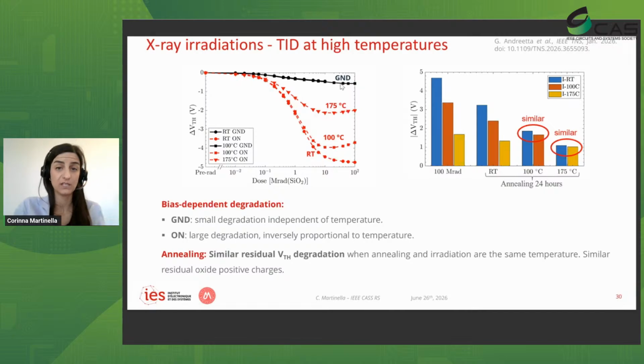However, when we are in on condition, we are in the worst case in terms of bias. And so we can see that at room temperature, the degradation was quite high, so down to 5 volts for 100 megarad, which again, it's very high dose. But then this damage recovers a bit for 100 C, and lower degradation is observed for 175 degrees C. So if we test at room temperature, we are actually seeing the worst case scenario. And then we perform some annealing.